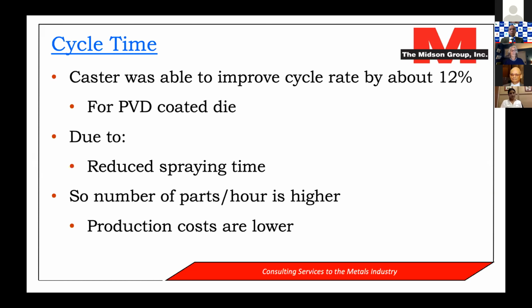And the first one was cycle time improvement. We were able to improve the cycle rate by about 12%, so cast 12% faster with the PVD coated die. Why? Because we weren't spraying as long. We used to spray 12 seconds, now we're spraying 1 to 2 seconds, so we can reduce the spray time, so the number of castings per hour is higher, and therefore production costs are lower.